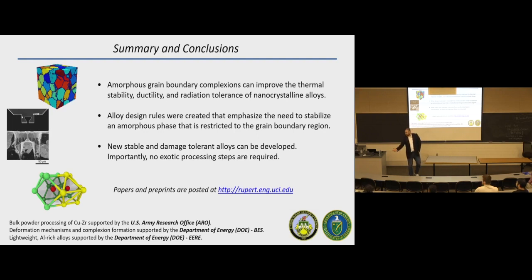I have a quick question. Do you think the state of this amorphous grain boundary will matter or not? For example, initially I designed it to tolerate dislocation absorption very well, but with time, with the loading going on, that capability is degrading or is losing. Initially, it can absorb, but with the plastic deformation going on. Well, yeah, because you do eventually overcome its ability to absorb more, so it will fail at some point.